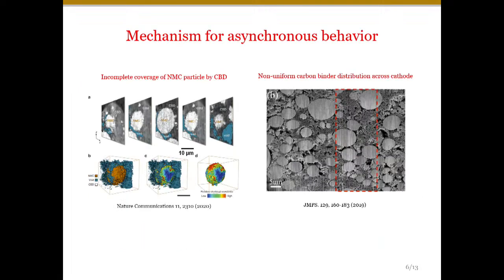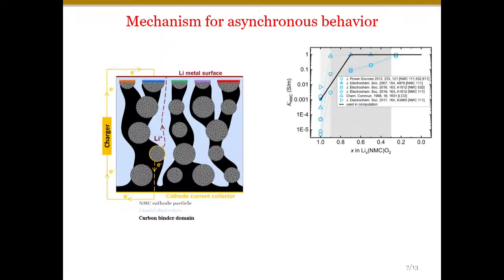In literature, as well as our previous work, we had already seen that carbon binder does not completely cover NMC in modern commercial batteries. There are a lot of voids and holes, and a very non-uniform carbon binder network. Based on that, we made a very simple model where the objective was not to replicate the experiment, but to provide the mechanistic understanding.